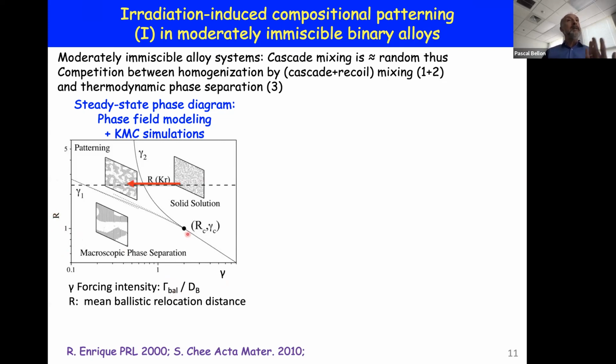What we see is that when R in these reduced units is small, the 2 steady states we are left with are, so to speak, trivial steady states. When the forcing is small, when gamma is small, this is a system that remains close to its equilibrium state. It is here in the state of macroscopic phase separation. When you increase the ballistic jump frequency, you can force the system, and the mixing becomes so dominant that thermal diffusion cannot keep up with that forced mixing, and the system ends up in a steady state that's a solid solution.